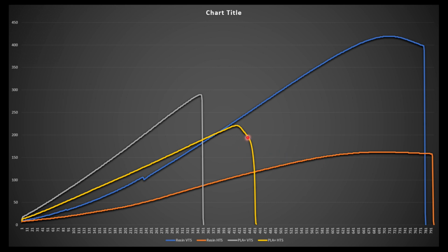So looking at this chart, you can see that the PLA Plus vertical test sample is very rigid. It's got a steep line, and you can see that the horizontal test sample printed from resin was actually quite flexible, and it appears that it stretched quite a bit before finally breaking. Now, if we look at the PLA Plus vertical test sample right here, you can see that it had no ductility. I don't know if ductility is the right word, but it didn't yield at all.